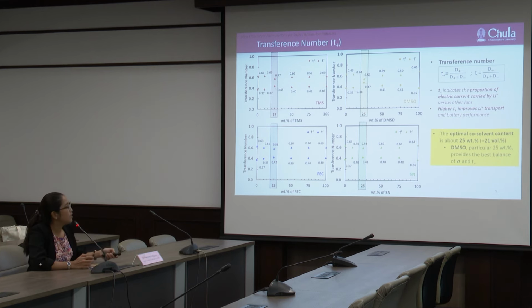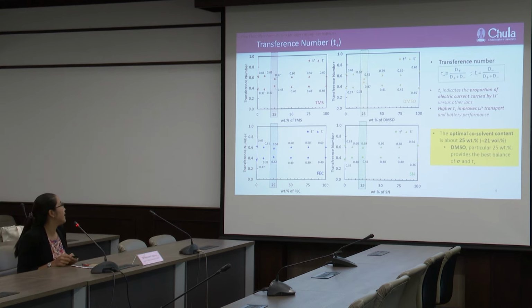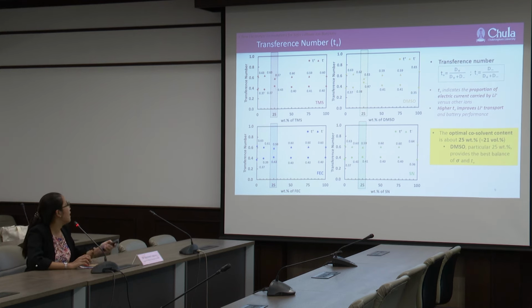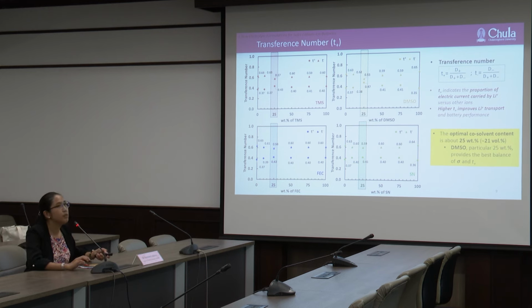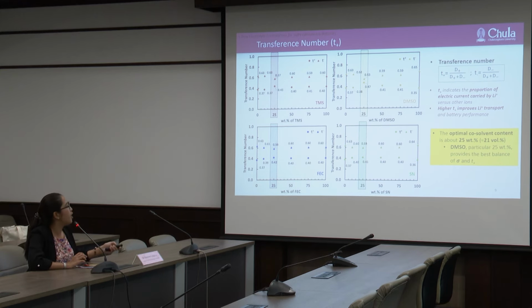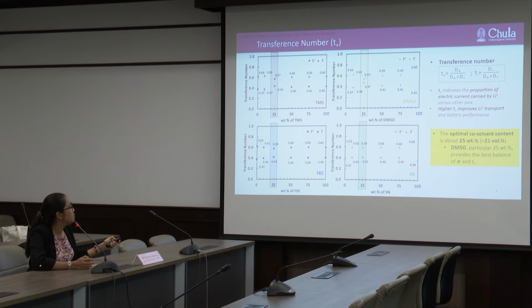Here I show the transference number. The lithium ion transference number indicates the proportion of electric current carried by lithium ion versus other ions in the system. Higher lithium ion transference number improves lithium ion transport and battery performance, and we find that the optimum co-solvent content is about 25%, and DMSO in particular at 25% provides the best both ionic conductivity and transference number. As you can see here, the transference number for the system that adds DMSO is higher than the others, about 0.47.